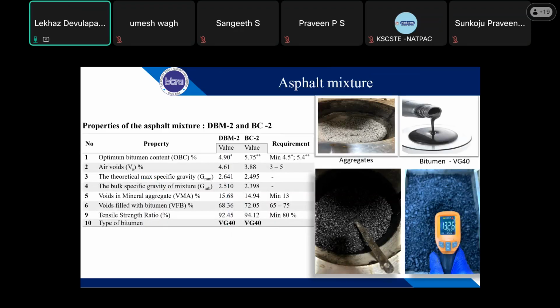We kept it constant, and then we used a VG40 bitumen, since almost all our highways are constructed with VG40. For that reason we chose VG40, and then we did a mix design for DBM2 and BC2. Why did we choose DBM2 and BC2? Because of the laboratory constraints and the NMAS of the aggregates. When we want to do the rutting test and the fatigue test, there are certain challenges in the laboratory to have the proper NMAS in the mix. The minimum thickness for the DBM2 was 50 mm, and for the BC2 somewhere around 25 to 30 mm thick. So because of that, we chose these two mixes for our research.